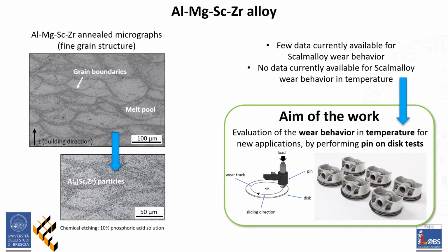What provides Scalmalloy outstanding properties is its microstructure. Micrographs of the cross-section obtained after chemical etching can be seen on the left. In particular, melt pools and the overlap of successive layers can be identified, which are the peculiar solidification structures of the process. Moreover, a stable fine-grained structure can be detected for Scalmalloy, together with particles containing scandium and zirconium and forming inside the aluminium matrix. These precipitates contribute to improve mechanical properties and provide low anisotropy.